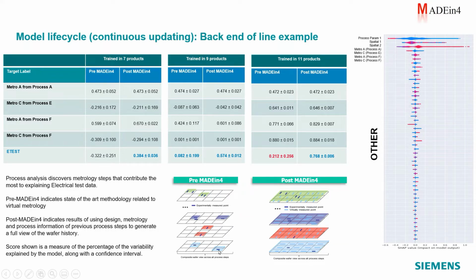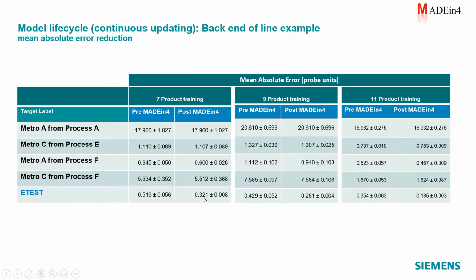We do not know, in that particular region of the wafer, what some of the other observations were that we had. With the work that we have done in Made in 4, we can actually construct a full description of how every single process step is virtually constructed. And that means that for every single point that we have at the end, in this case the electrical measurement, we have a full stack of the different measurements that are accounted for. We can see how, from the point of view of e-test, the error decreases from 0.3 to 0.26 to 0.18, but also you can see that the confidence interval gets tighter.